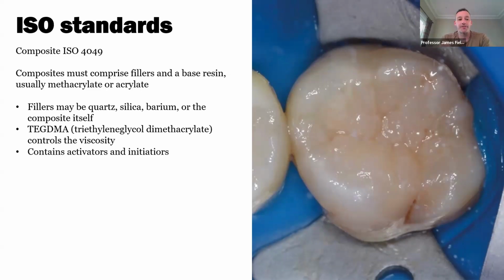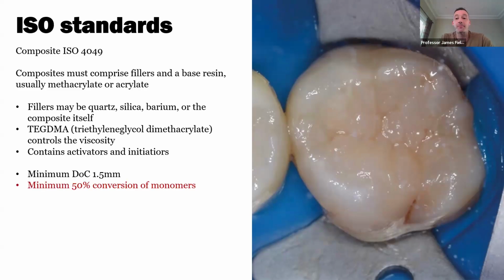And in there as well, we have what are called activators and initiators, which determine when that curing cycle begins, and when it does begin, how that moves through the material, and make sure that as much of the material as possible is being cured and polymerized. So the ISO standards say a few things. They say, first of all, that the minimum depth of cure for any composite has to be 1.5 millimeters. For them to be sold as dental composites, they have to do that. They also have to have a minimum of 50% conversion of their monomers to polymers.